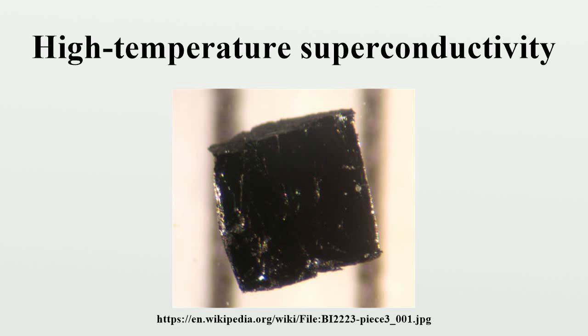YBa2Cu3O7-x compound. At the time of sintering, the semiconducting tetragonal YBa2Cu3O6 compound is formed, which, on slow cooling in an oxygen atmosphere, turns into superconducting YBa2Cu3O7-x. The uptake and loss of oxygen are reversible in YBa2Cu3O7-x. A fully oxidized orthorhombic YBa2Cu3O7-x sample can be transformed into tetragonal YBa2Cu3O6 by heating in a vacuum at temperature above 700 degrees Celsius.